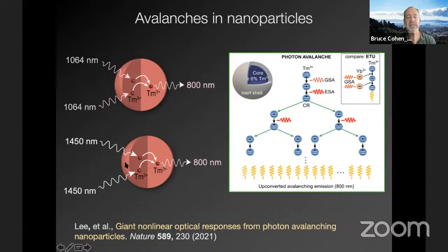One of the other things that's interesting here is thulium can absorb light as well further into the near infrared at 1450 as well. But it doesn't actually have an absorbance at 1064. Thulium's absorbance peak is 980. So we are effectively exciting a couple of phonon vibrations away from that 980. So it's very counterintuitive that you can excite not at the peak and get much better behavior like this.